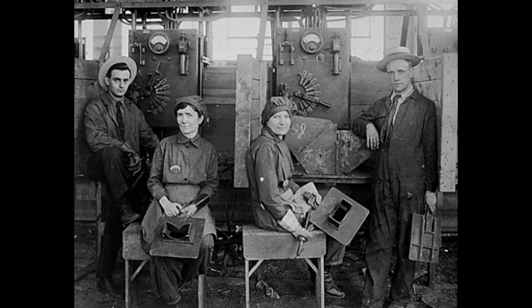Investigators noticed something else. The failures occurred predominantly in cold weather. Ships operating in the North Atlantic were far more likely to crack than ships in the Pacific or Mediterranean. The SS Schenectady had failed in January in Portland, Oregon, where temperatures hovered near freezing. Other ships reported cracks after passing through winter storms. The temperature correlation was undeniable but unexplained.